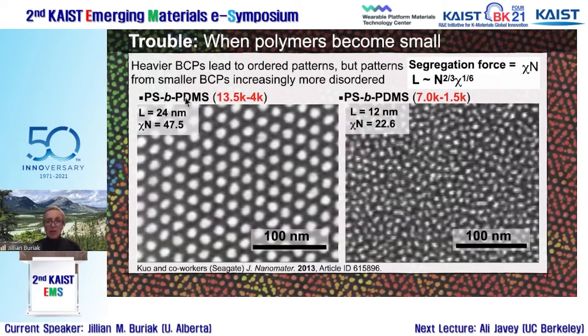So in this case, choosing the same block copolymer. So again, this is work from Seagate. So polystyrene PDMS. So I put the molecular weight of the 2 blocks here in red. It has a center to center spacing, often represented in the field by L. So the center to center spacing is 24 nanometers. Looks pretty good. Nice hexagonal patterning. When you choose the same block copolymer but smaller molecular weight, the center to center spacing is 12 nanometers, represented by L. But you can see the one on the right just looks awful. Okay, so that's because something called your segregation force is diminishing. And so if you take this to the extreme where the polymers get smaller, at some point they just simply isotropically mix.